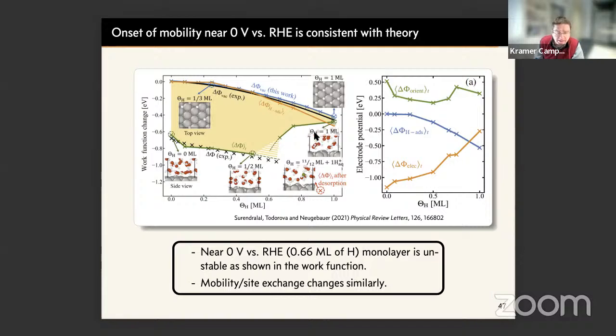So it's a bit complicated if you're not a chemist. What is plotted on the left is the work function. This black line is the experimental work function in vacuum. This is the energy it requires to inject an electron to the vacuum level as a function of hydrogen coverage. One way to interpret a CV is that it is an effective work function for the electrochemical environment. And if you do that, you can write the experimental work function for the electrochemical environment. This is shown here in these black X's.